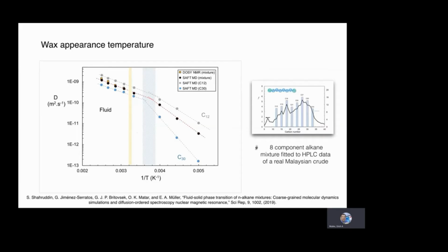So this is the output of a simulation of a multi-component alkane mixture fitted to a real Malaysian crude. And the interest here was to look at the wax appearance temperature, which is basically related to that point in the self-diffusion curve where there is a change in the slope. So we saw this change in slope, with the mixture in red matching very nicely to the NMR data for the fluid region and predicting a wax appearance temperature quite close to the experimental data.